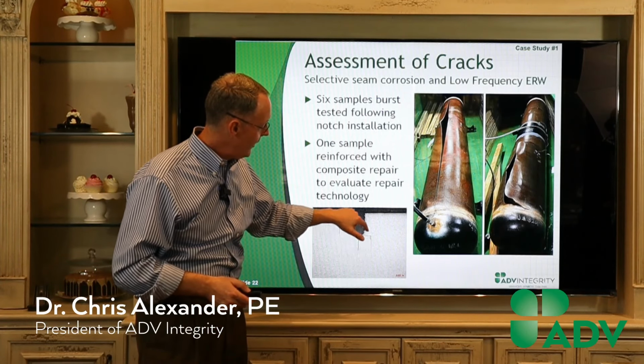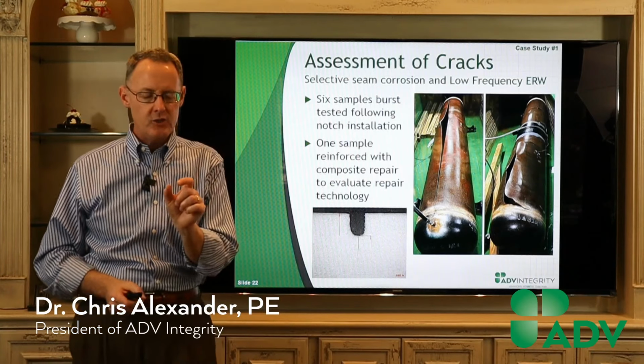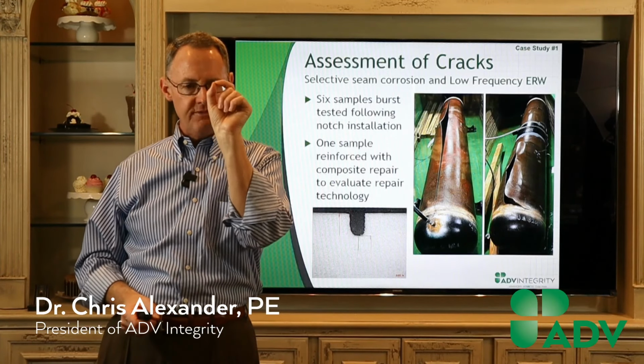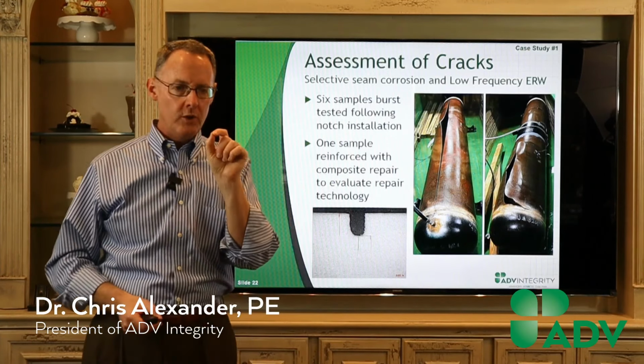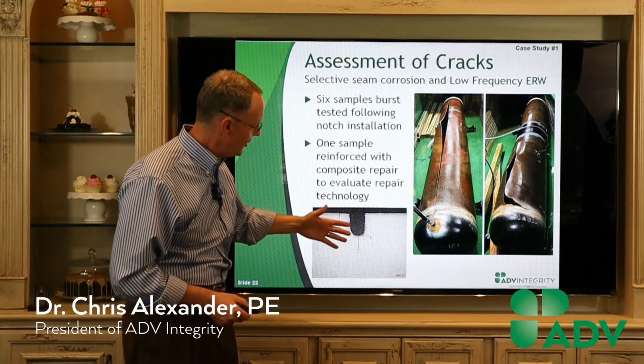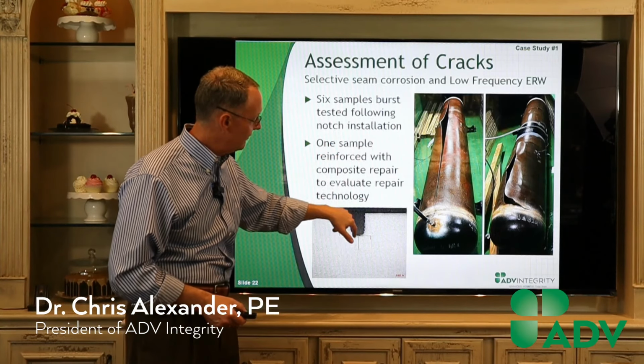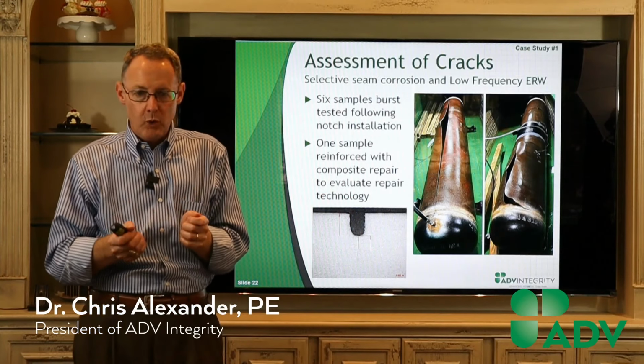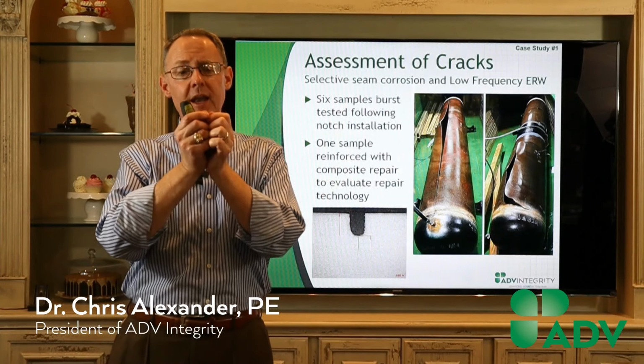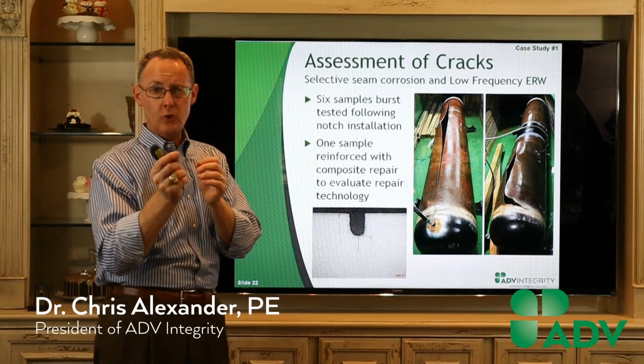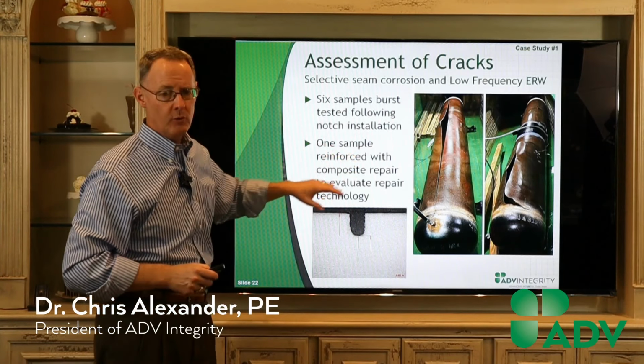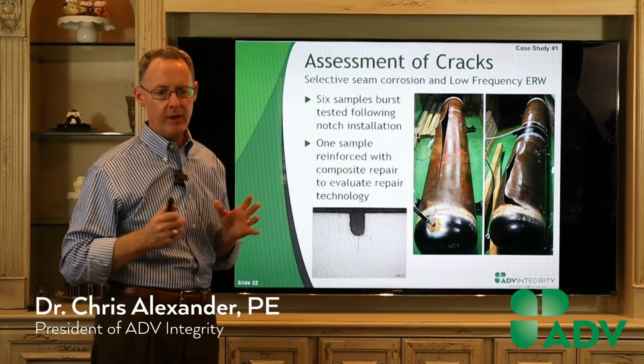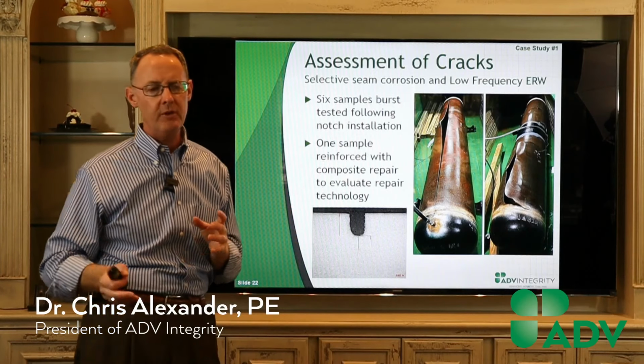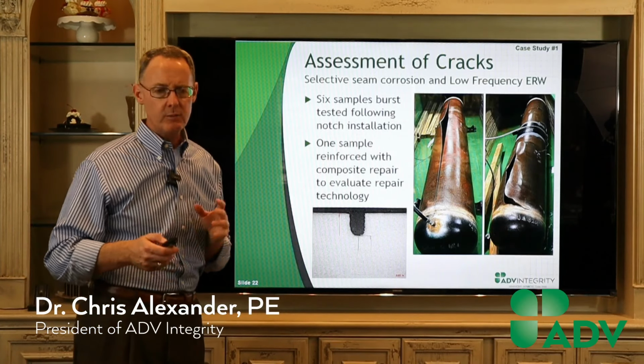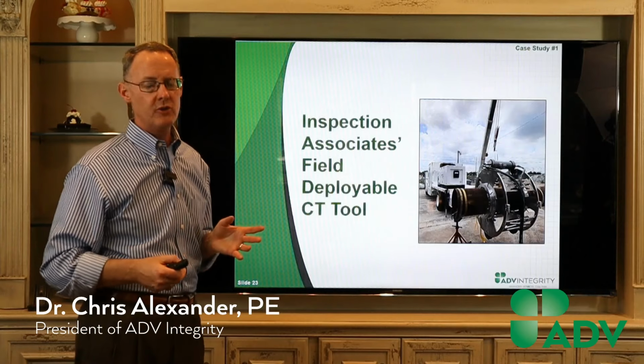So one of the things I want to point out right here, if you notice in this image on the left, is we have an EDM notch, and it's interesting, to the naked eye, it looks very, very sharp, but when you zoom in on a microscope and you do a macrograph, you notice that it's very round. So when we do the pressure cycling, we wind up creating a notch. The notch turns into a crack. So that's a lot of what we're doing right now. Probably in the next 6 months, we're probably going to make well over 100 of these on a couple of different projects. And so we've got some technologies that allow us to monitor that.